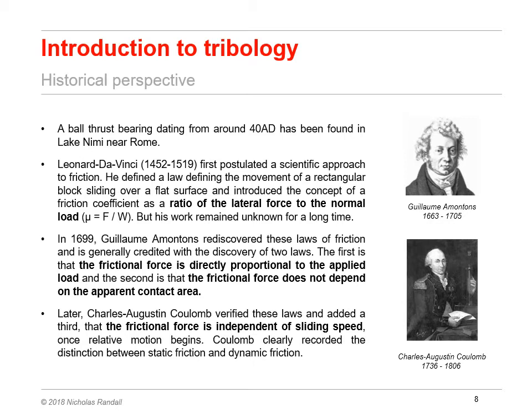So we have three important historical contributions to the theory of tribology. Leonardo da Vinci first introduced the concept of a friction coefficient as the ratio of the lateral force to the normal load. Guillaume Amontons postulated that frictional force is directly proportional to the applied load, and that frictional force is independent of apparent contact area. Coulomb then distinguished between static and dynamic friction, and found that frictional force is independent of sliding speed once relative motion begins, at least over a certain range of speed.